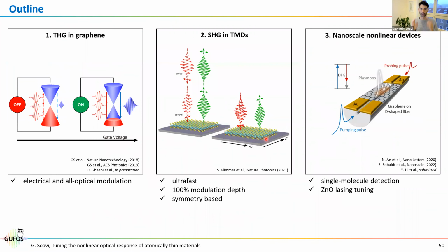So, third harmonic generation in graphene, I've shown you both electrical and all-optical modulation. Second harmonic generation in TMDs, I've shown you one method to achieve all-optical modulation that is based on symmetry considerations and gives 100% modulation depth and the highest possible modulation speed. And this might have applications in pulse characterization, but also in light structuring.